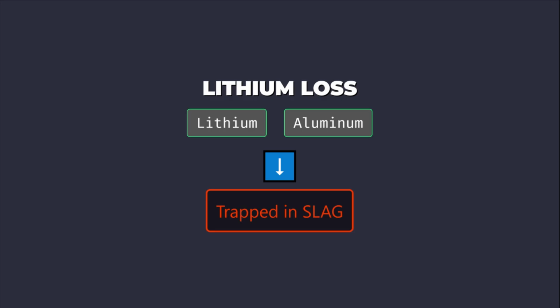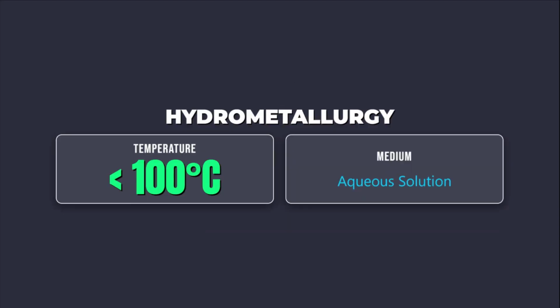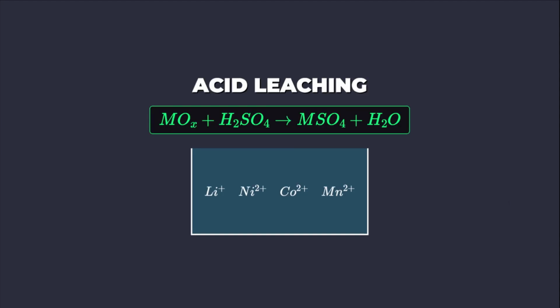The high energy demand and the loss of valuable lithium, which is increasingly critical for battery production, are the primary drawbacks of this approach. Pyrometallurgy effectively destroys the cathode crystal structure, requiring complete resynthesis of new cathode precursors. Hydrometallurgy uses aqueous solutions to selectively dissolve target metals from the black mass. This approach operates at significantly lower temperatures, typically below 100 degrees Celsius, reducing energy consumption compared to smelting.